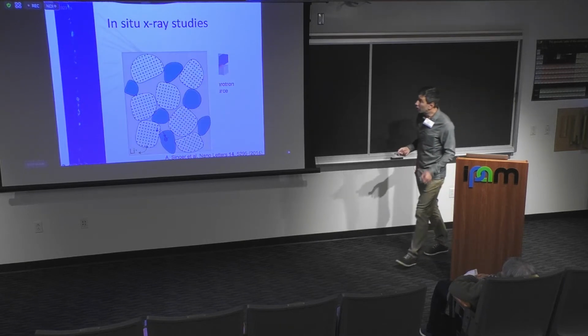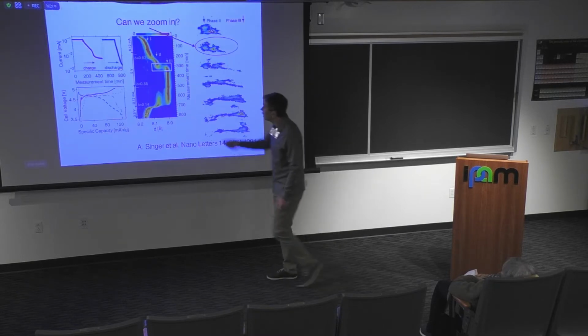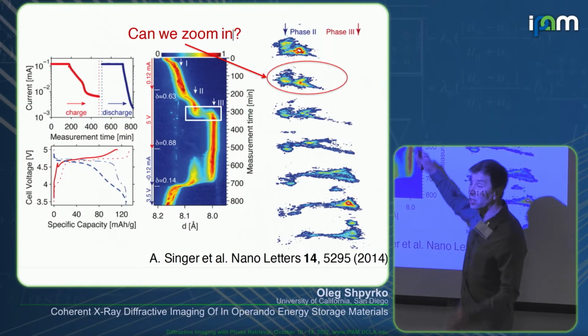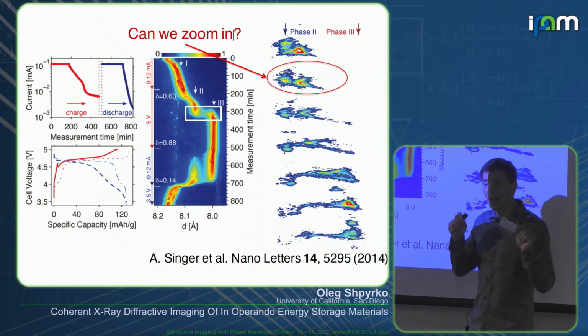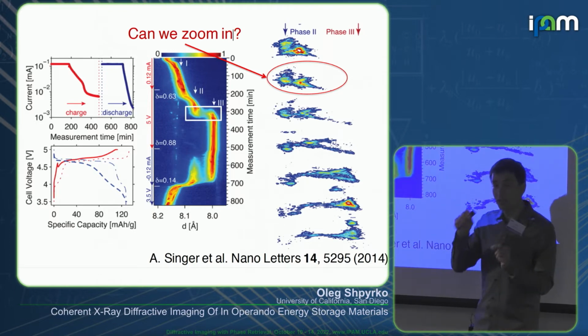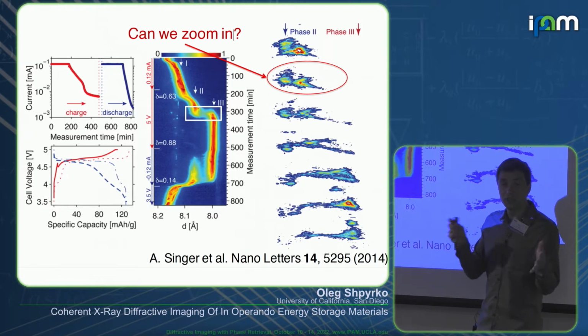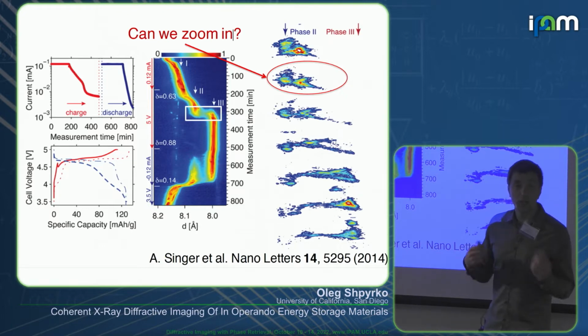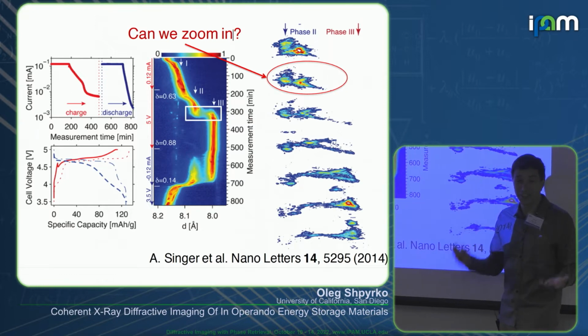Okay, so there are many ways that you can analyze it. Let me jump through this. I already talked about this. So this is the dimension. I'm playing this again, but let me jump to this a little bit faster. So we can plot the diagram for what happens in the charge-discharge state, and we can see the hysteresis, and we can do this for a large ensemble of the particles. But because we have access to a finite, discrete number of particles, we can analyze it particle by particle and see what is the distribution in terms of how each particle goes through the phase transition and back individually as well as an ensemble, right? So from the engineer's perspective, this is the greatest thing ever.